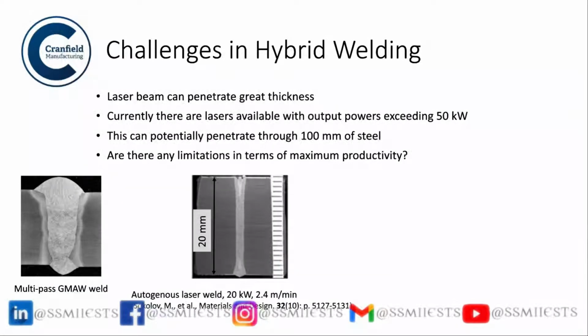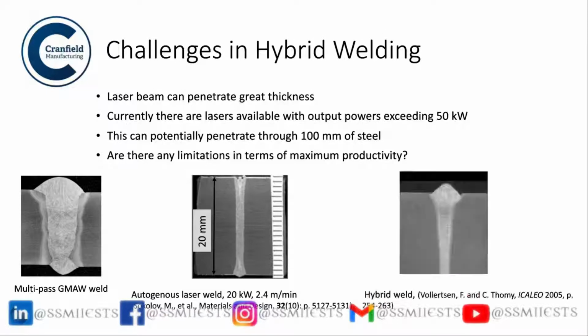Here are some examples which were done by previous researchers. So multipass GMAW welds. It is very good, but it is quite slow. The heat input is high and stuff. This is pure laser weld. However, this part will be incredibly weak because it is molten parent alloy and didn't have any strength whatsoever, and it might have even a martensitic structure or something because of the higher cooling rate in the heat affected area. And this is a hybrid weld.